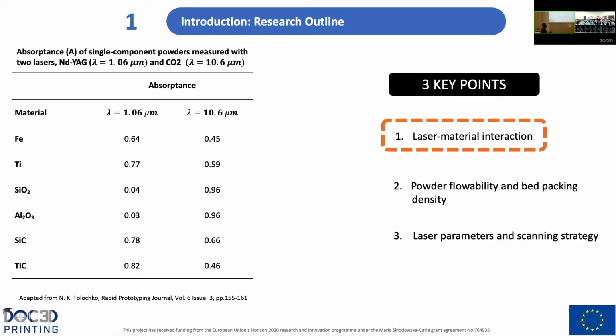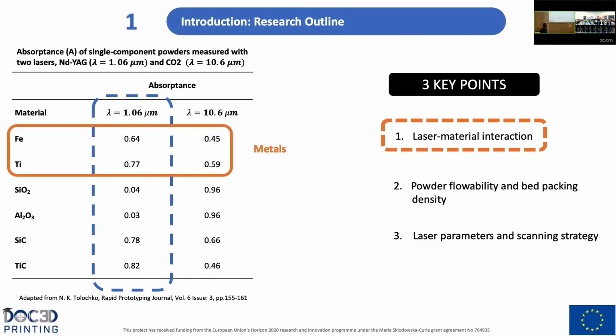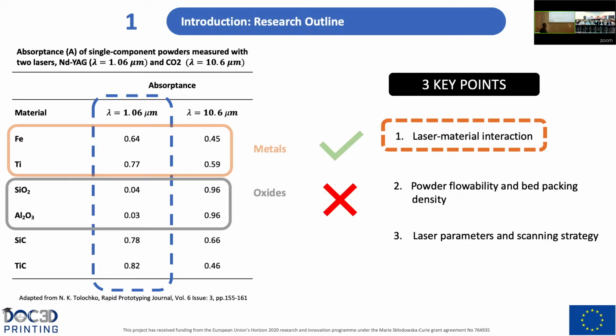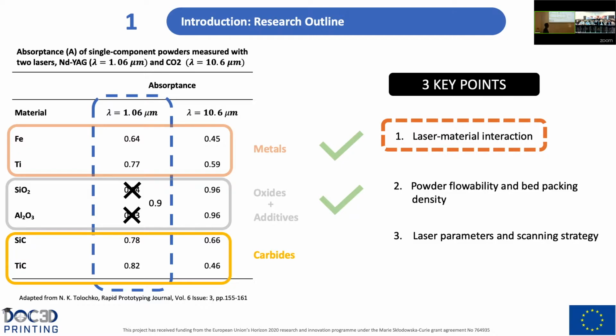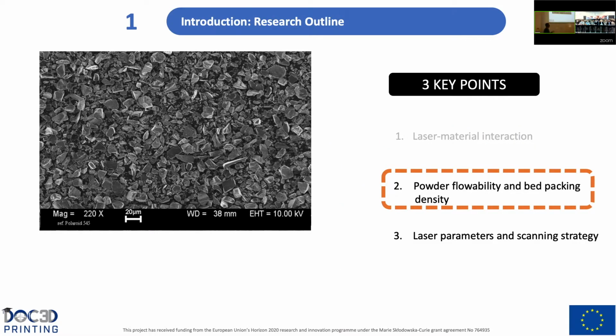So in our particular case, in this work, we will work at this wavelength. For example, if we are using metallic parts, we see that we have a good absorbance for this process, and we can work with them. For other materials, such as oxide ceramics, we see that we don't have a good absorbance, and researchers have adopted as a strategy the addition of some additives to enhance the absorbance, and now we are able to work with them. And in our particular case, for carbide ceramics, we have a very good absorbance, so they are ready for this process. Next step is to assure a good powder flowability and a good bed packing.